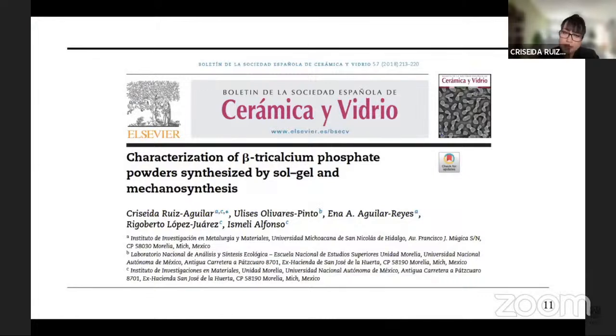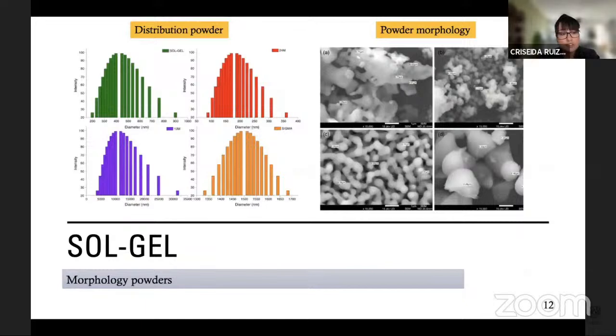Then I'm going to show some results of my research lines about the calcium phosphate and bioactive glasses. In this article, a comparison was made between sol-gel and mechanosynthesis techniques to synthesize beta-tricalcium phosphate, and the results obtained in this investigation allow us to understand the effect of the synthesis method and the particle size of the tricalcium phosphate powders. To conclude, the sol-gel particles were smaller than the mechanosynthesis, as you can see in this slide. And the method permits us to understand that the milling time and the revolutions per minute are variables that affect greatly the particles of the tricalcium phosphate.